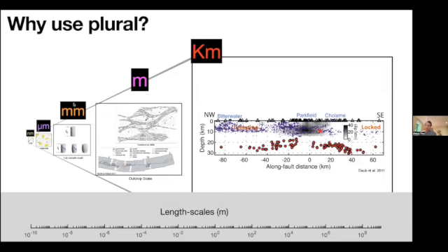Now, in the laboratory, at the millimetric sample size, the definition of a brittle-ductile transition is such that if we deform initially intact rock and we see that a fault developed, then we call this deformation brittle. And if we see that the sample barreled and there's no obvious macroscopic localization into a fault, then we call this deformation ductile. Now, the localization of strain along faults is one of the prerequisites for earthquakes and for rapid motion along faults, but not all faults need to generate earthquakes, and can also occur during slow creep processes.